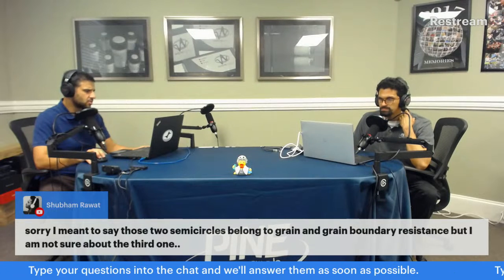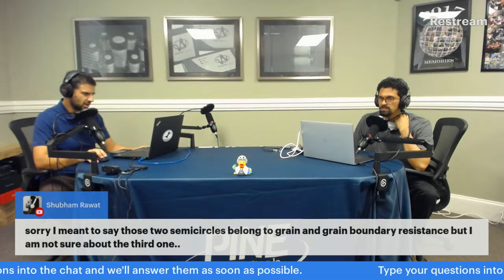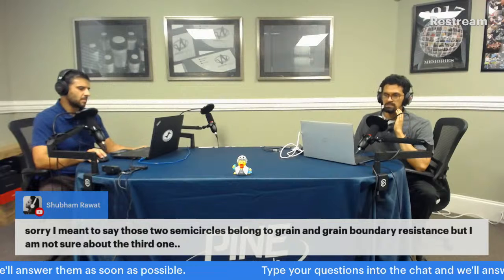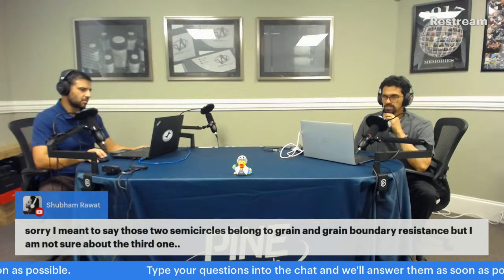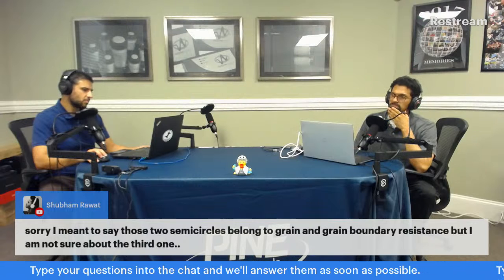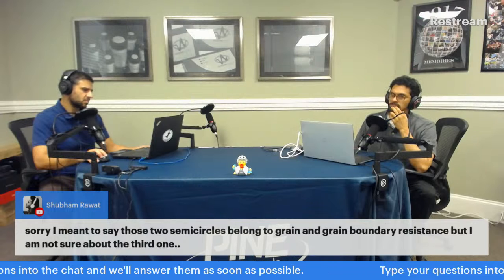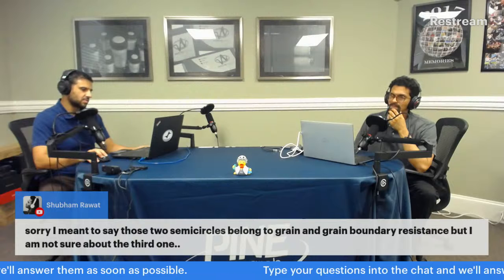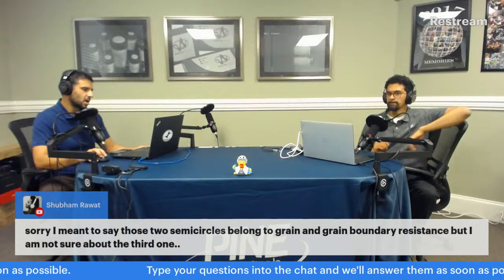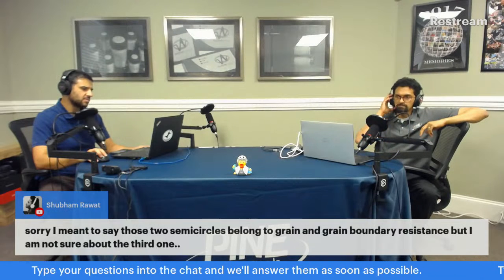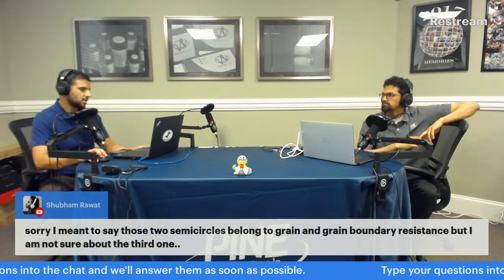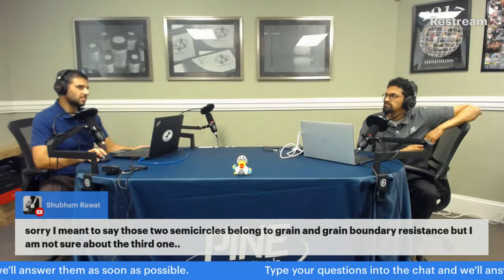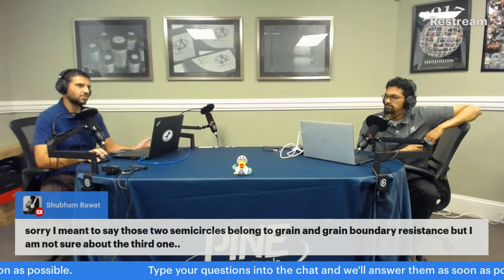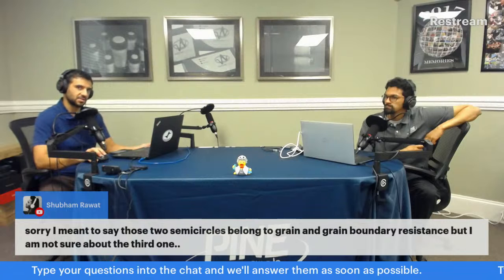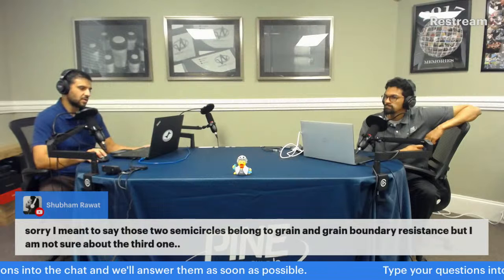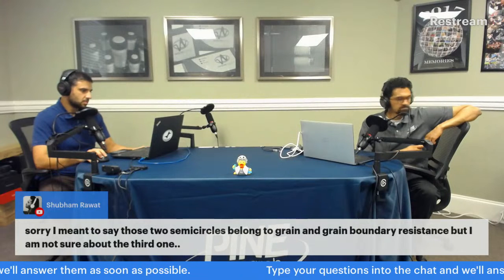So I meant to say that those two semicircles belong to grain and grain boundary resistance, but I'm not sure about the third one. So not solution resistance, but you mean grain boundary resistance. Well, even then you're still talking about a grain boundary resistance. That sounds like an interface, but if you have a semicircle, it means there's some interface, right? And so if it's a grain boundary resistance, there must be some coupled capacitance associated with it.